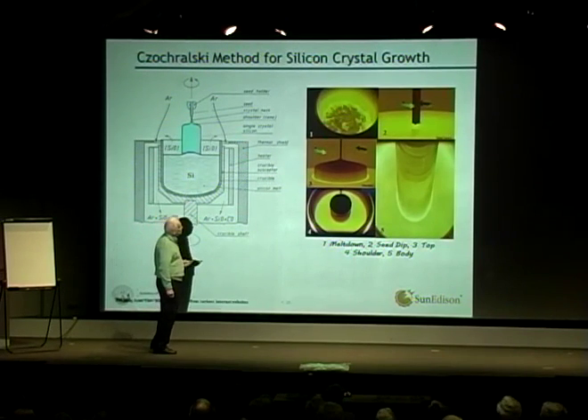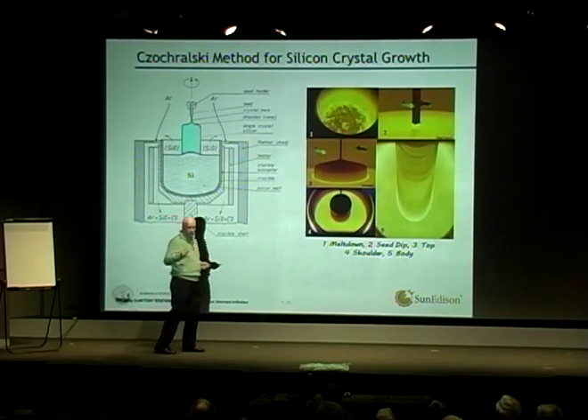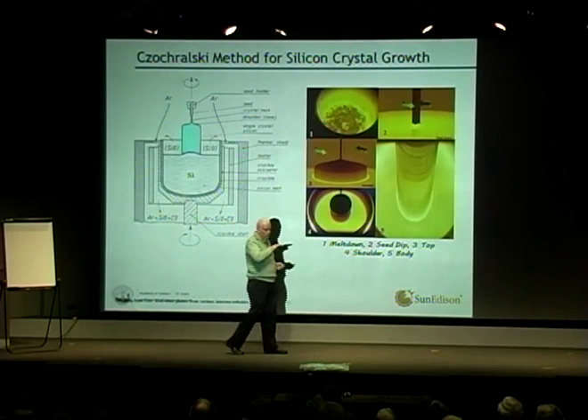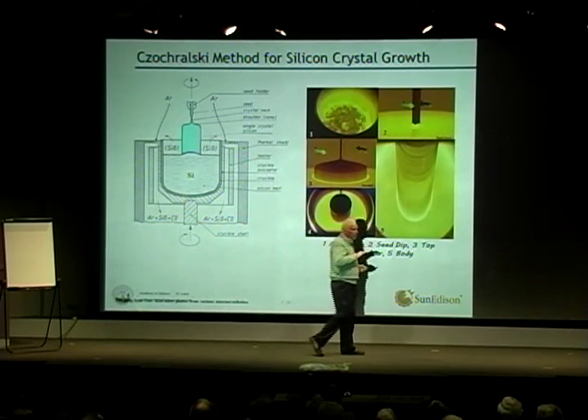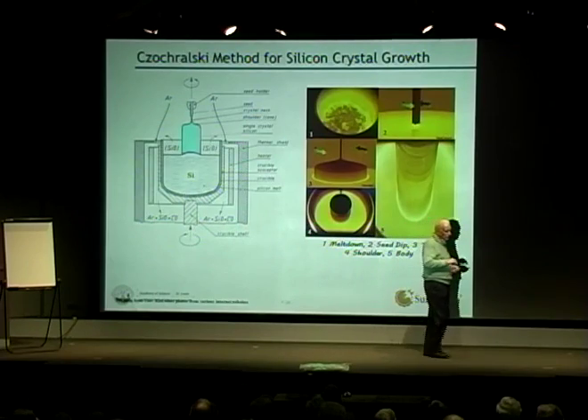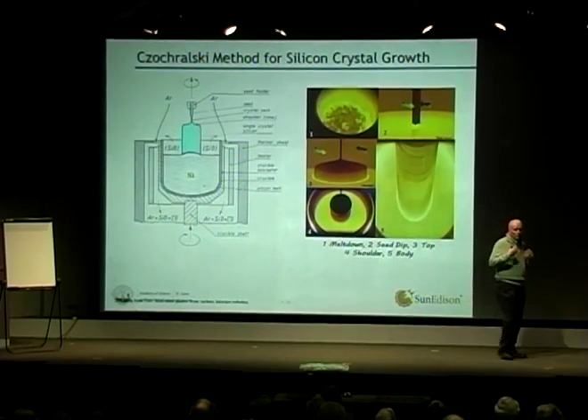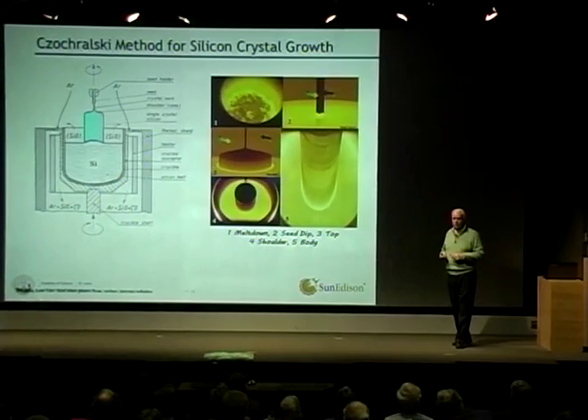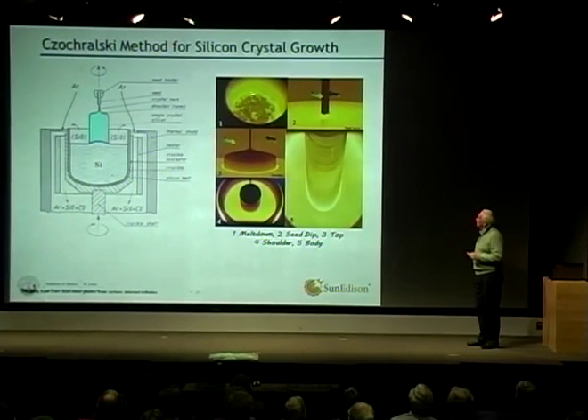Here it is. These pictures, by the way, are taken through a piece of glass covered in a thin layer of gold. The reason is you have to coat it in gold because otherwise it'd be white hot and you wouldn't be able to see it or take a decent picture because it would be too bright. That's why you get all this yellowy color. But we put the polysilicon here, we heat it to about 1410 centigrade and it melts.